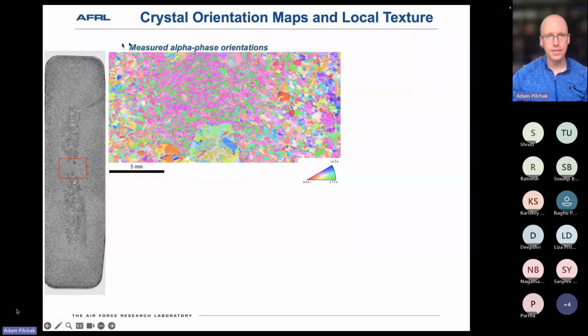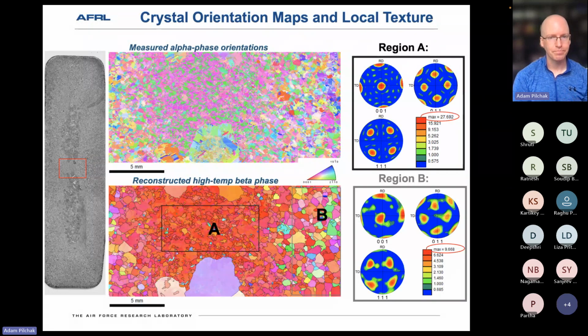And so this is the measured alpha phase data set that was collected. So you can see the large beta grain popping in down here. What we're calling the fine grain halo is this mixture of purples and greens, so nominally 2 orientations. And then when you get out to the nominal microstructure, typical 1 millimeter or so beta grain size is filled with colonies. You see a variety of different colors indicating a little more random texture, though it's not perfectly random.